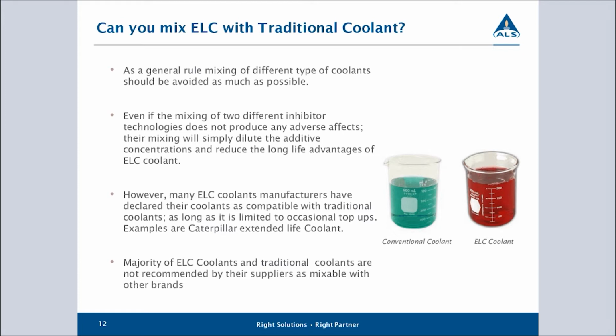out of there. The problem is that because different coolant manufacturers use quite different chemistries in their coolant, when we start mixing these together, we can get reactions between these additives, and these reactions can be unpredictable unless we properly understand the formulation of each of the coolants. So the general advice is not to mix coolants if at all possible.